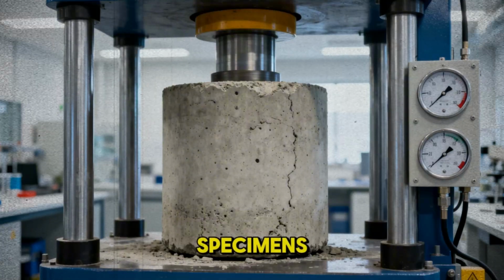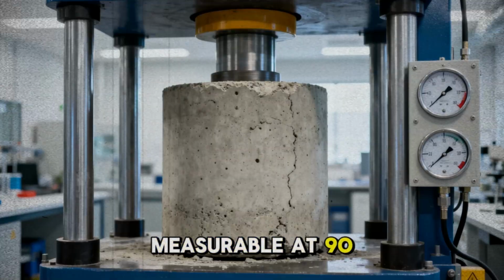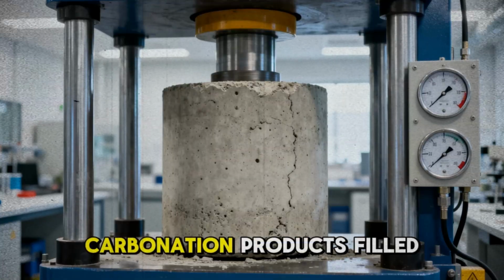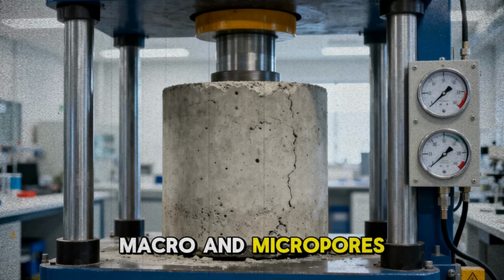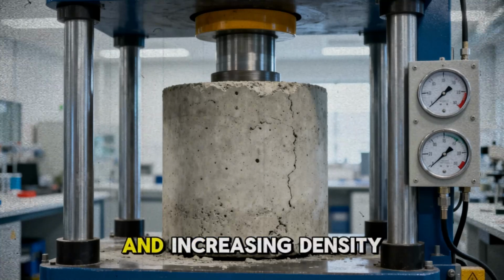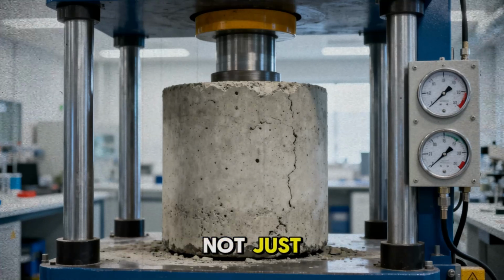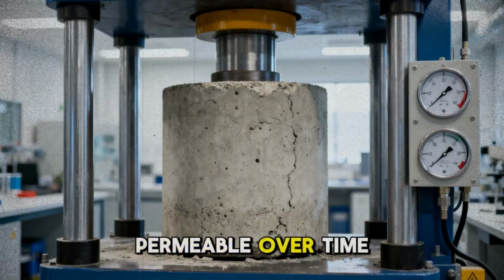In some test specimens, strength gains were still measurable at 90 days and beyond. The crystalline carbonation products filled macro and micropores progressively, reducing permeability and increasing density. The material was not just stronger, it was becoming less permeable over time.